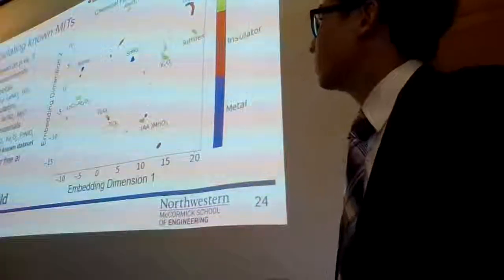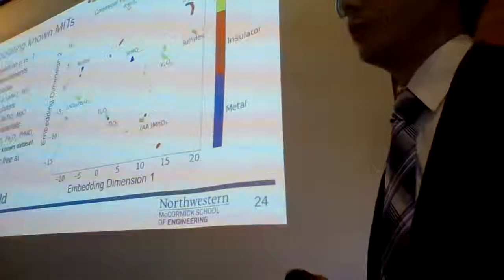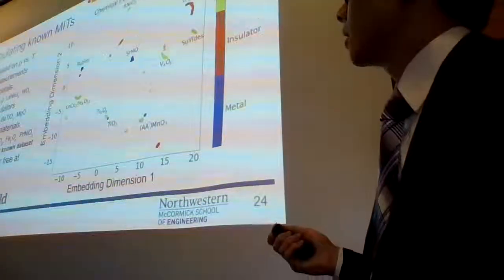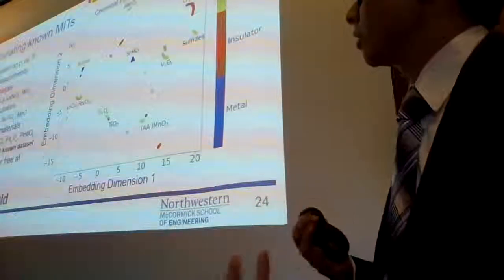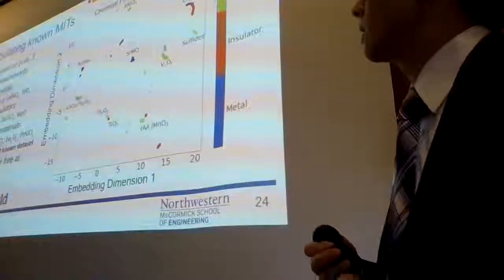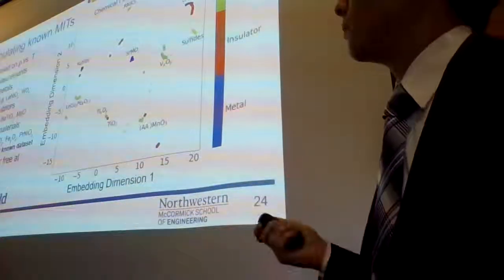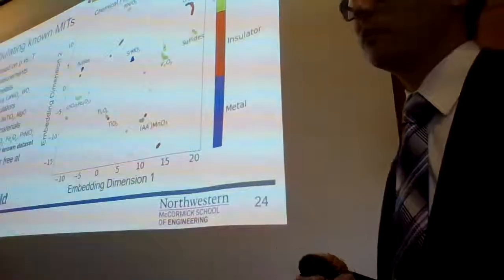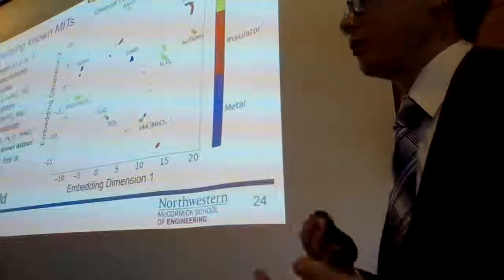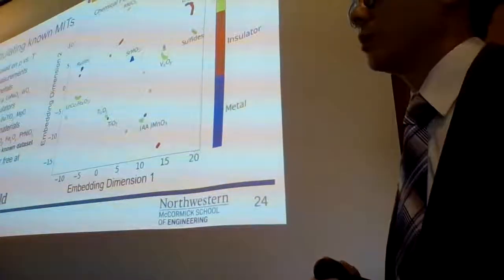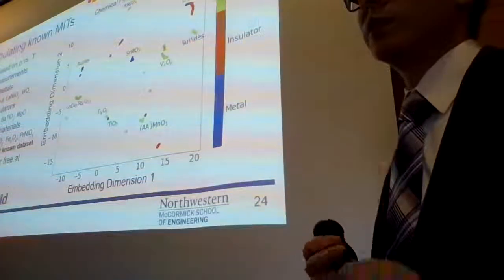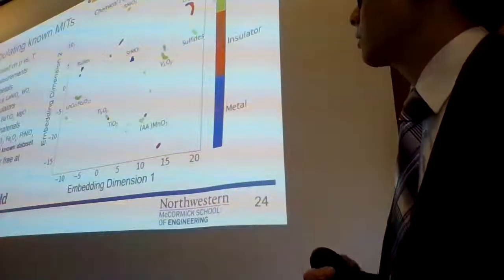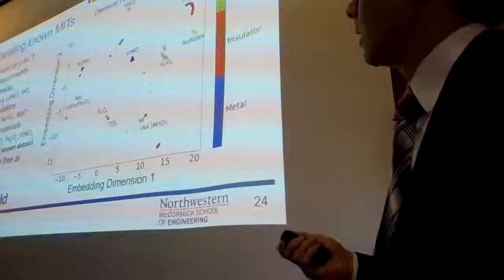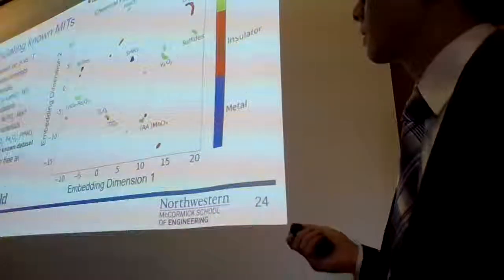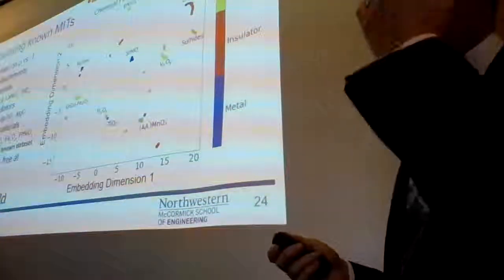To do that, I first had to collect known labels. In my case, because it's based on metal to insulator transition, I looked at experimental reports of resistivity versus temperature data, because I consider that the most reliable. I understand there are other ways you could base this criterion. But given the known limitations of DFT in predicting some band gaps, I figured it was the safest way to do it. And I primarily focused on transition metal oxides because those are the materials most commonly associated with metal insulator transitions.